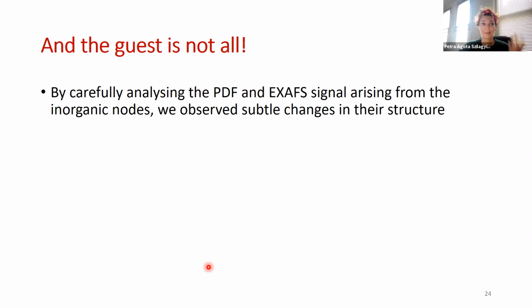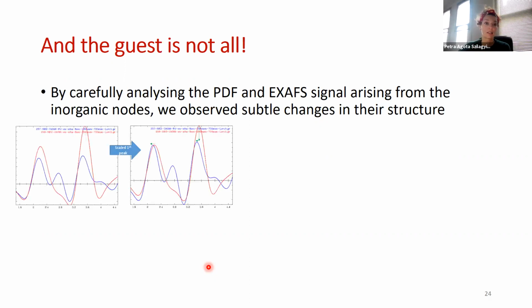But the other example I want to show is perhaps a little bit more stunning, because normally we would be looking at the inorganic nodes, the clusters, as quite stable and unchangeable in a sense. And we found that when we add palladium to the amino UiO-66, and particularly when we reduce it, and I would like to say that this is PDF data here, where we had already removed all the palladium contribution.